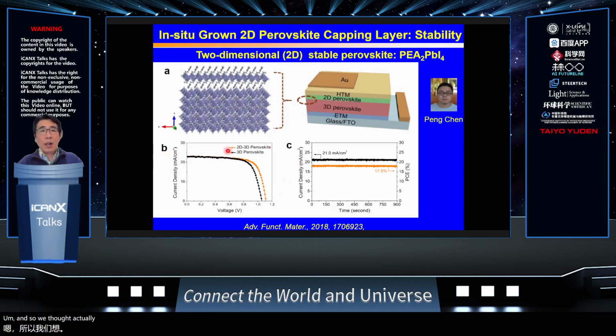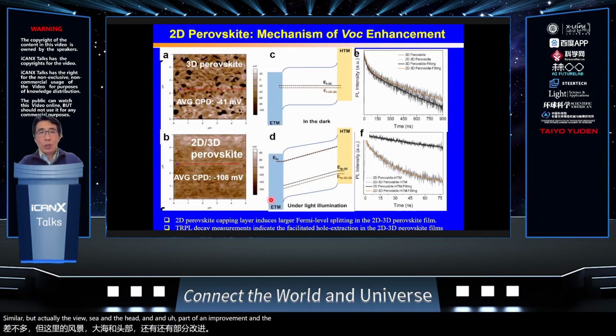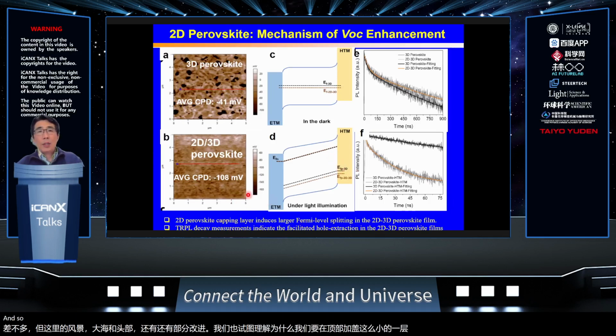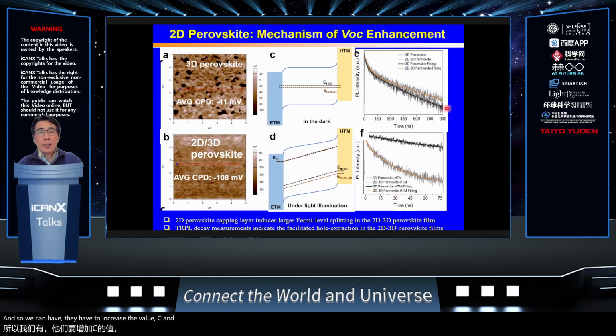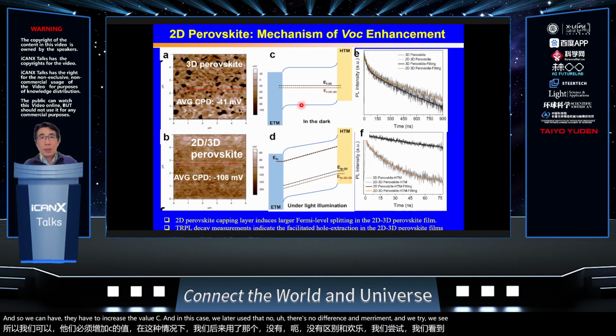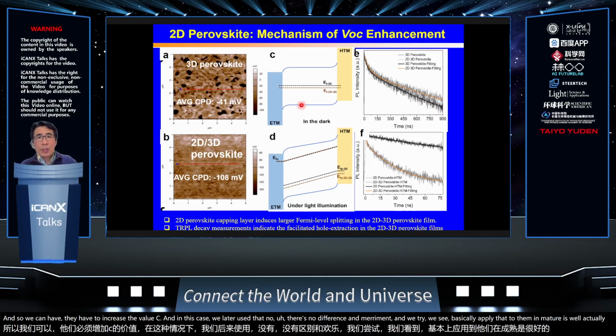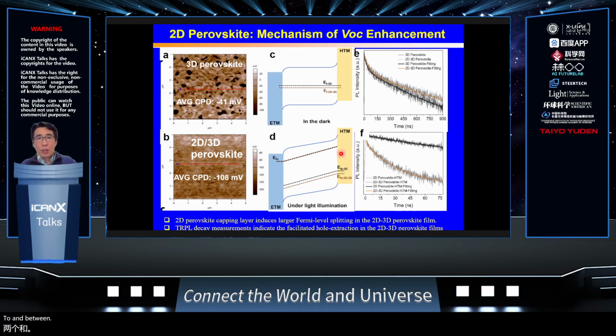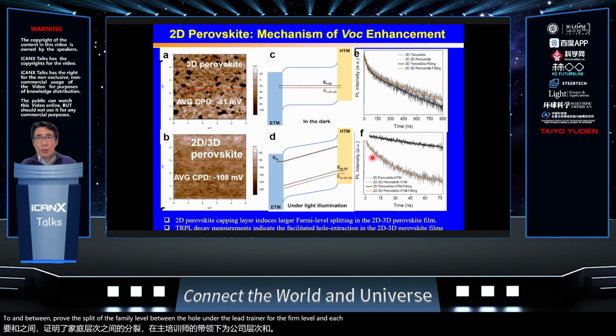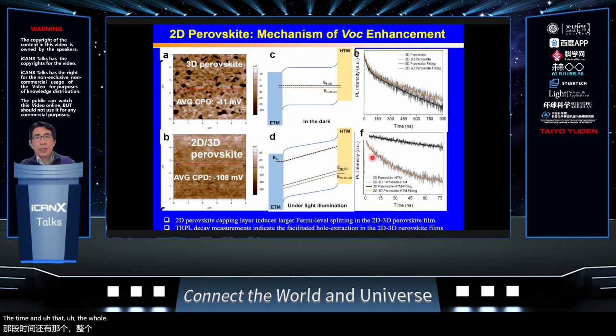And we found the other parameters were all relatively similar, but the VOC actually had quite a good improvement. We tried to understand why applying such a small capping layer on top can help increase the VOC. In this case, we used the contact potential difference measurement, and we see that applying the two-dimensional material helps to improve the split of the Fermi level between the hole and the electron quasi-Fermi level, which will facilitate the hole extraction in the device.